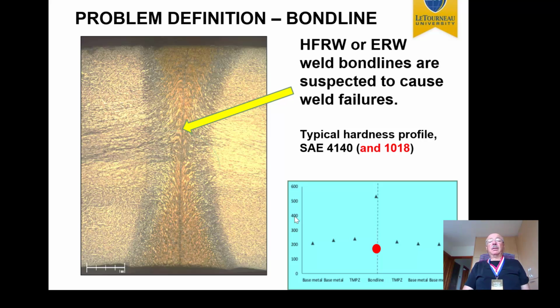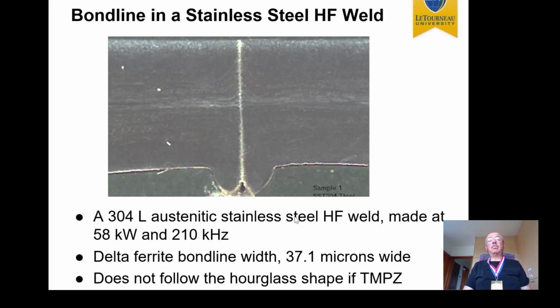So it has a weird behavior, this particular bond line, and also, if you notice, it doesn't follow the hourglass shape of what we call the thermomechanically processed zone, a TMPZ, highlighted there. So the bond lines are always straight, no matter what kind of material, what kind of shape the TMPZ has. Here's an example of an austenitic stainless steel 304L made at 210 kilohertz, 58 kilowatts. We talk about very high powers. But you'll see what this is.